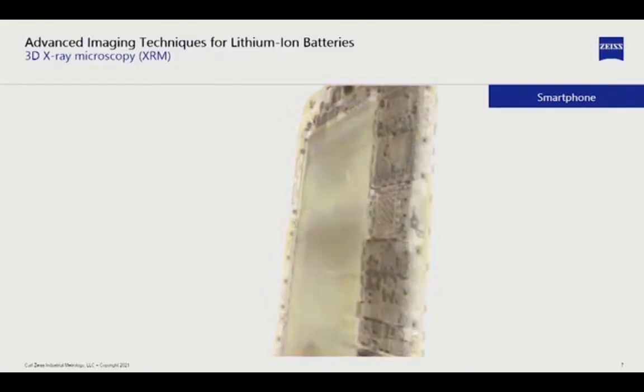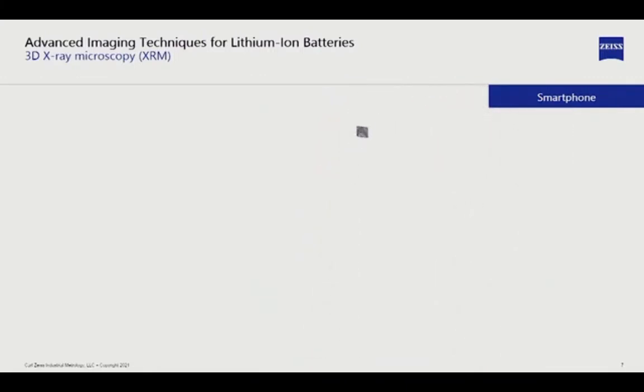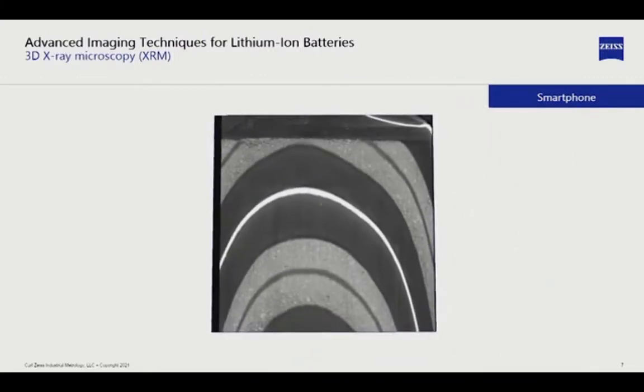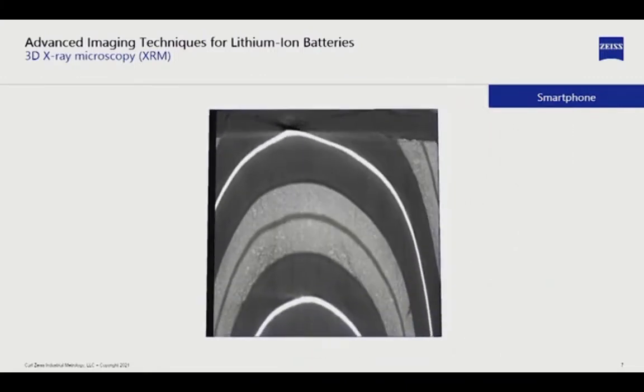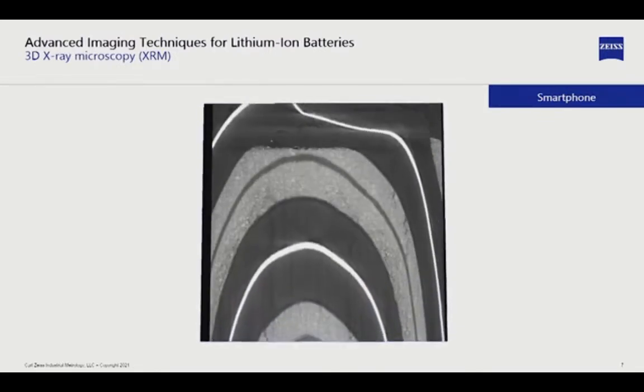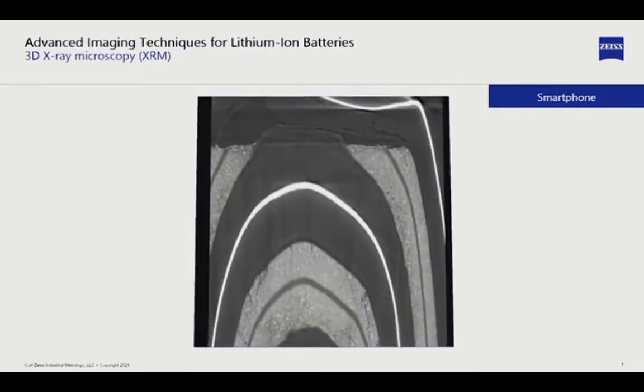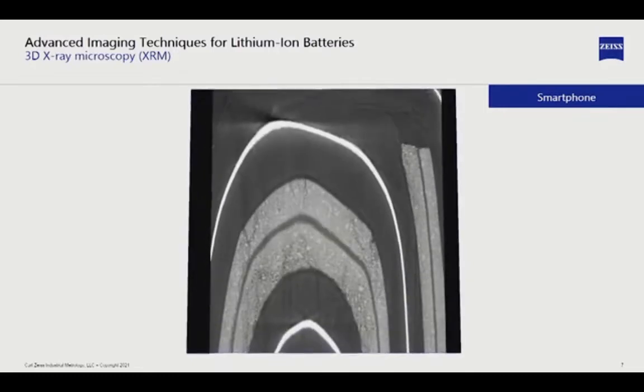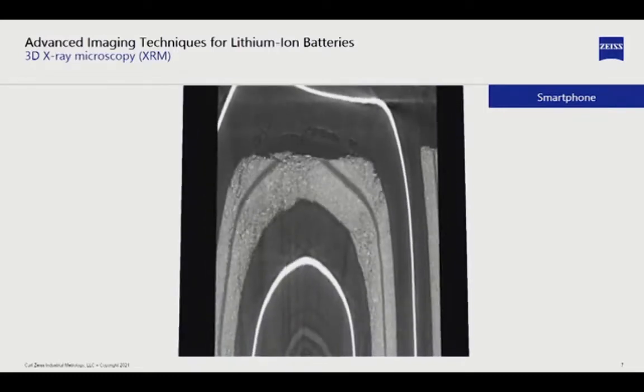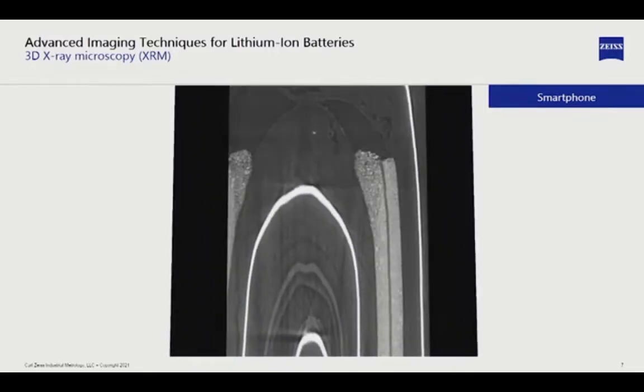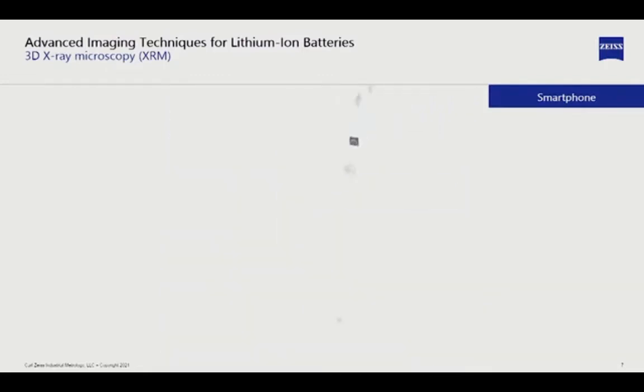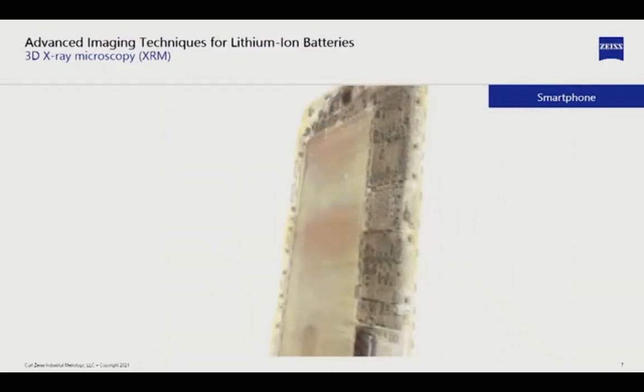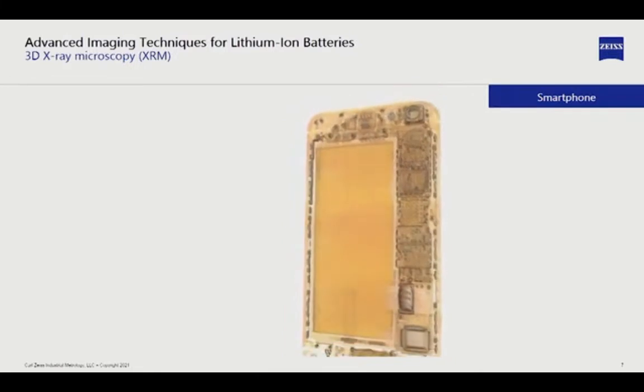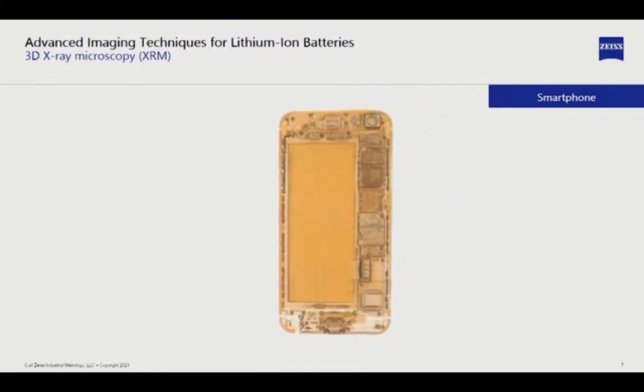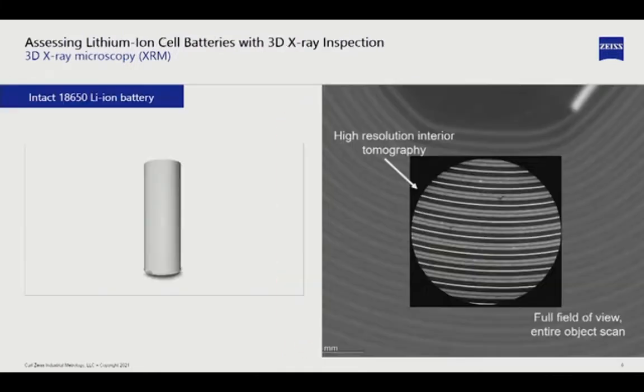Yeah, there it is. That is how you can scan a device like a smartphone and check inside the battery without destroying the device. And check inside the battery for the composition of the electrodes and see if there are any defects, cracks or delamination that can be caused by charging and discharging cycles several times in the battery.